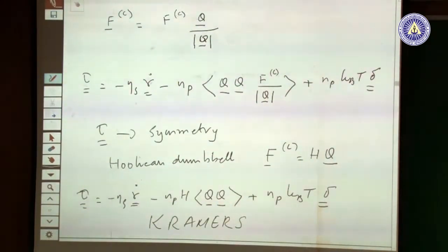So what are the diagonal components? Qx squared, Qy squared, Qz squared. Only if they are the same will their difference be 0. It will turn out in simple shear flow it is not, and that is why it contributes to a normal stress difference. If it was zero normal stress difference, this is a Newtonian fluid, then there is no point in this entire exercise, right.